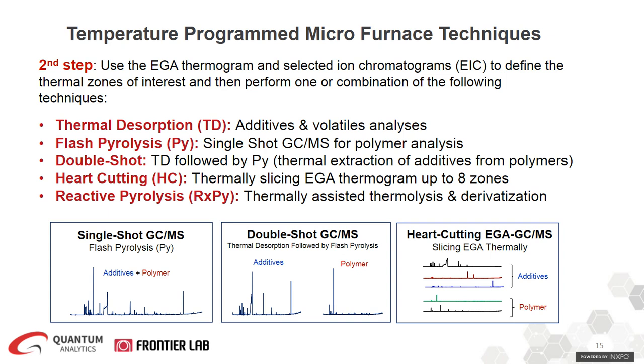Okay, so whenever you perform your EGA, of course, you want to have it from a lower temperature all the way to higher. For example, say you program your furnace from 100 to 700 C, then compounds start evolving. So at that point, you can start analyzing your EGA using the Frontier EGA-MS and also extracted ion chromatogram, EIC, and then identify the appropriate thermal zone.